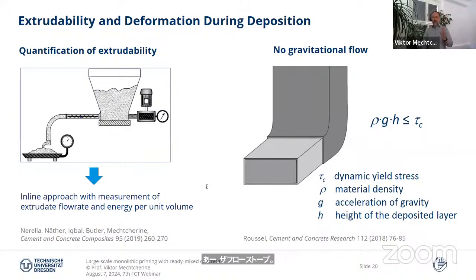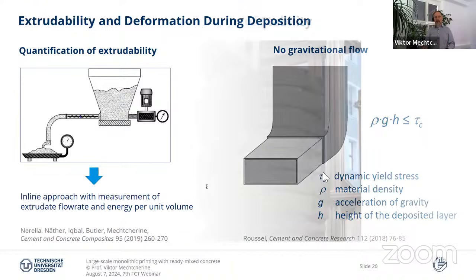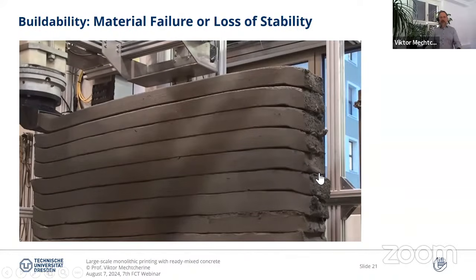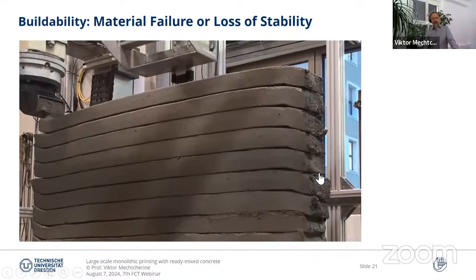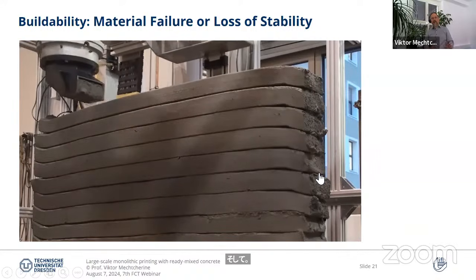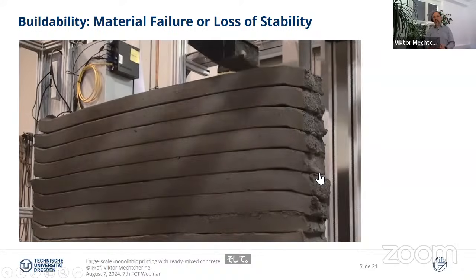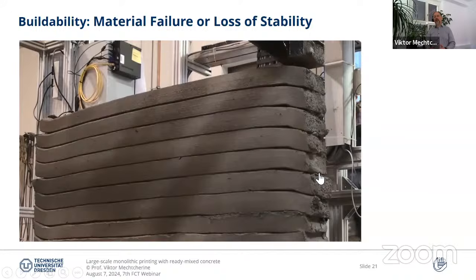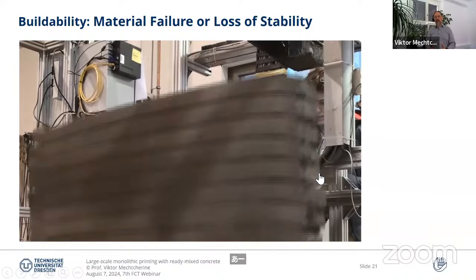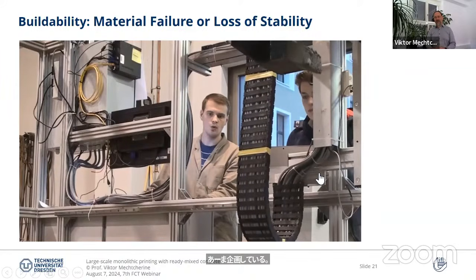Good. You probably noticed that in our approach, we try to keep the shape of the nozzle so that we have a very good control over the shape of the element, since we also use pretty large filaments in the deposition. So this is an example from the lab. In this case, it's already about buildability. So we look at what would be the limit when we place material layer by layer, and how well we can predict the failure of the material if the building process is pretty fast. And this is done here, of course, on purpose. So we want to see the failure so that we can check if the prediction works well.